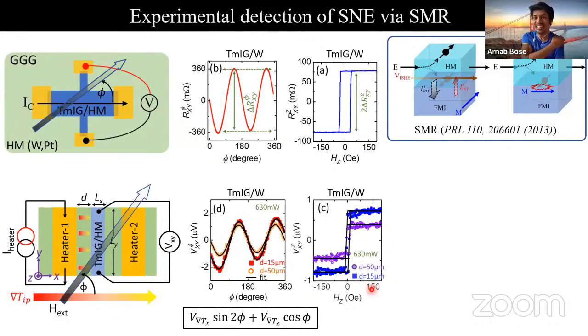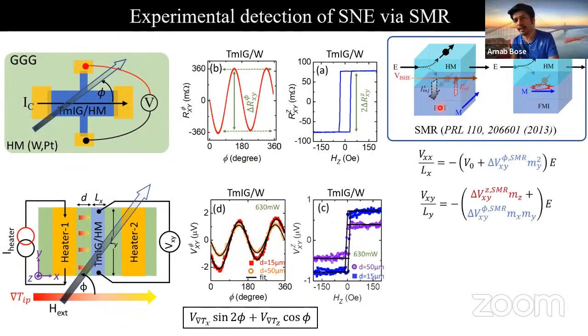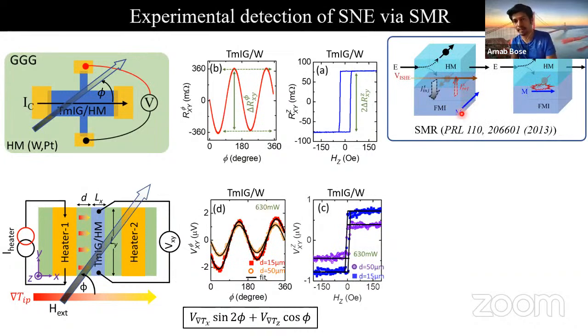So one of the possible origins could be the electrically and thermally driven spin Hall magnetoresistance. Just to remind you what happens in SMR. When electric current or electric field is applied in a ferromagnetic insulator/heavy metal bilayer, again, the electric field could be applied by applying electric current or by applying thermal gradient, we can get the transverse spin current. And depending on whether they're collinear with the magnetization or not, they can transduce back to the inverse spin Hall voltage, and if they are orthogonal, then they will scatter and don't contribute. So this will result in both longitudinal and transverse magnetoresistance. And indeed, the transverse magnetoresistance can mimic a PHE signal, even if the magnet is insulating, and also it can mimic the AHE-like signal.